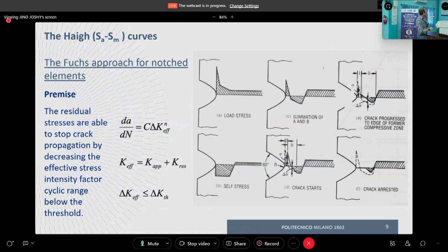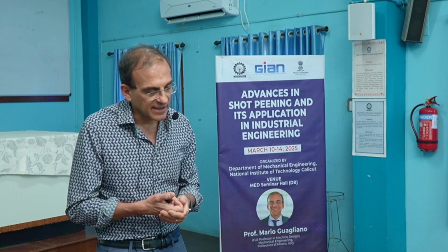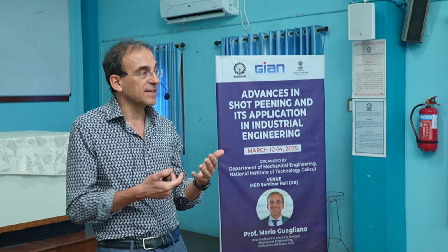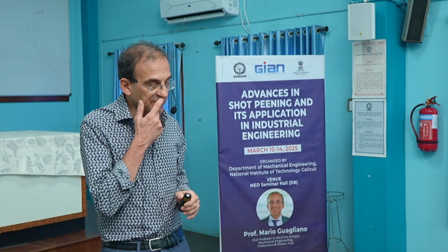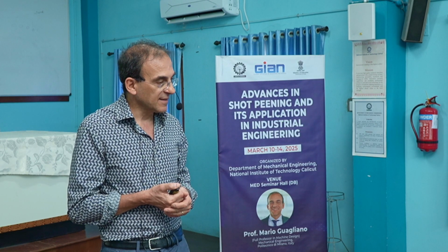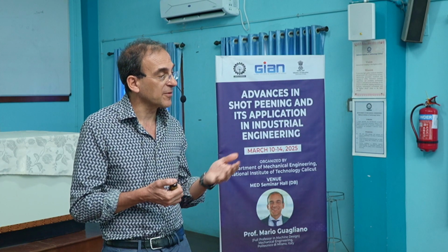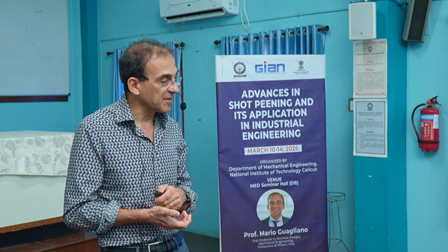We have already commented on this figure, and I don't want to comment on it again, but just to recap, the result is that even if we have a residual stress field, even if a crack is able to develop at the notch root of a notched part, it can start growing, but it will then be immersed in a residual stress field. Due to the steep gradient of the stress, soon it will run into a compressive stress field that is able to stop the propagation. So we will have parts with some microcrack that is no longer running, due to the effect of residual stresses.